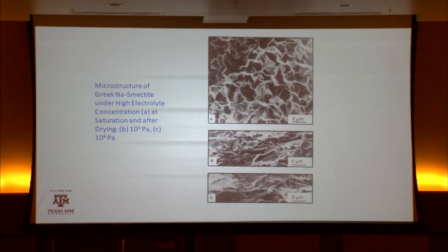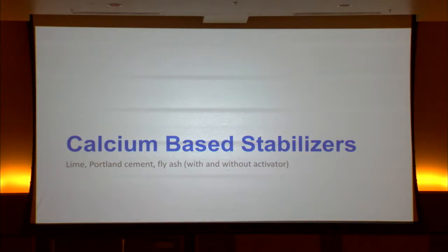Here's another picture. This is from a book by Dr. Wilding of the soil science department here at Texas A&M. He did this years ago looking at vertisols. We have vertisols all over Texas. And he just shows the extreme change in the microstructure of clay. This is fully hydrated, where the layers are pushed apart because of that water that's held interstitially. And then as we apply suction to it, you can see that those layers collapse, and more suction collapses them even further. So there's your swell mechanism.